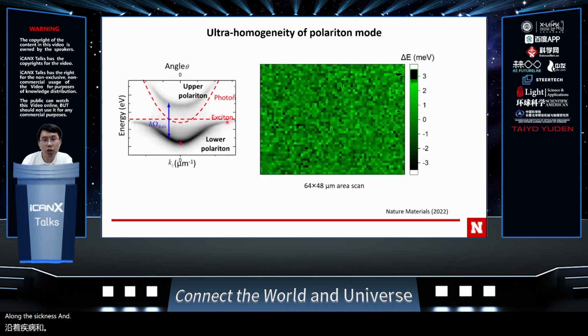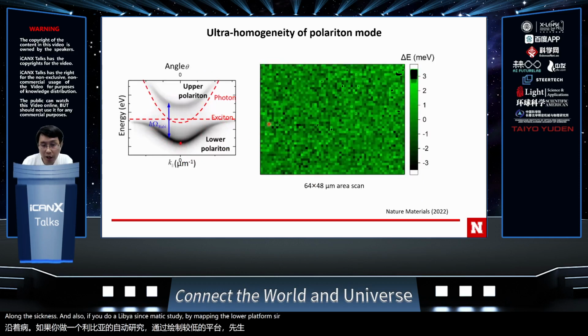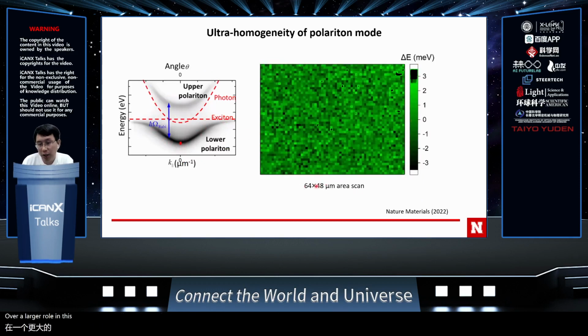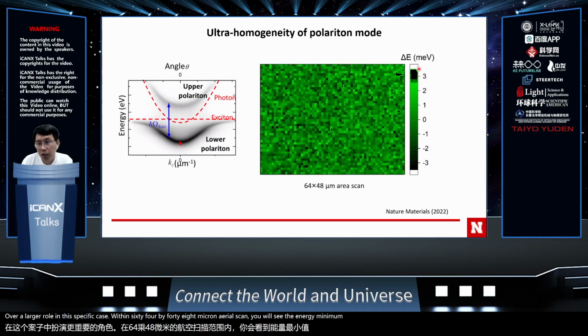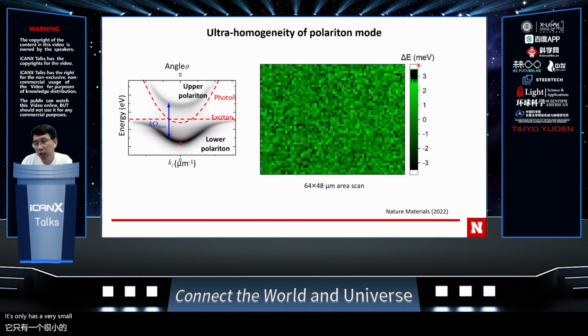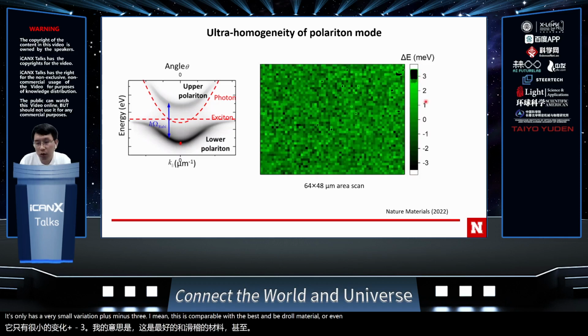Also, if you do a systematic study by mapping the lower polariton energy level spatial distribution over a large area, in this specific case a 64 by 48 micron area scan, you will see the energy minimum has only a very small variation, plus or minus 3 meV. This is comparable with the best MBE-grown material, or even superior, for example gallium arsenide or cadmium telluride.